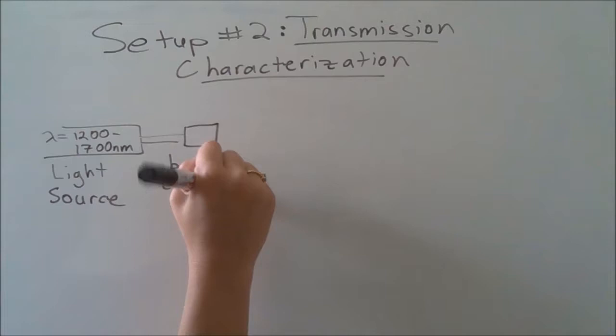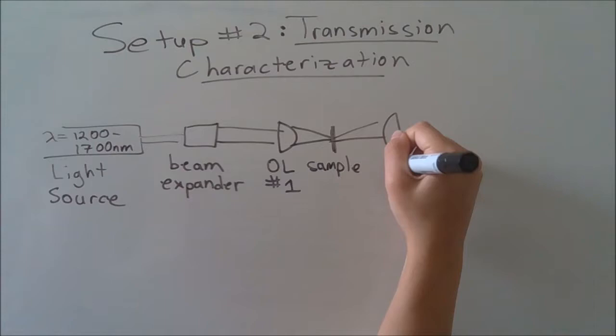and the periodic spacing of the laser's movement. We then characterized the transmission spectrum of the gold nanostructures using another optical setup, where a light source such as a broadband laser or a halogen lamp was directed through the structure. A spectrometer was used to measure the transmission of the light, first through the structure and second through the surrounding gold layer.